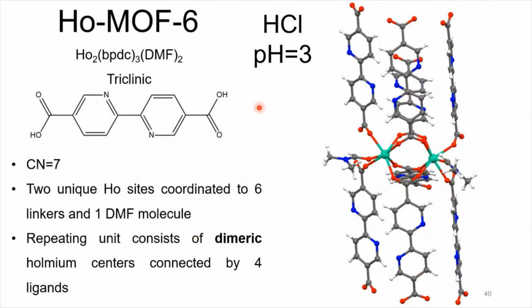Now, if we change, and this is normal when you are trying to grow single crystals, one way to slow the growth of these crystals is by adding acid. And if you slow down this crystal growth, then you end up with nicer, bigger crystals. But what we ended up with here was a change in the coordination number. And now we actually see our solvent DMF. In the previous one, we also had DMF, but it didn't react with the holmium center. But here it definitely did, and it changed the whole structure.